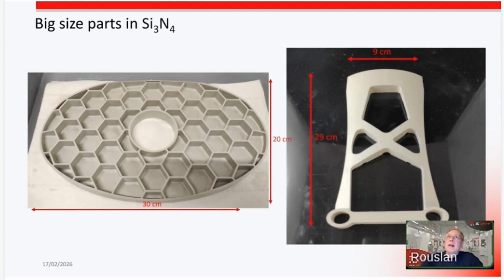So why am I saying this? It seems to be big, but when the shrinkage is repeatable and we really control it, we can apply the scaling factor. With some challenges, however. With machining, your part is fixed. You have a zero point to fix the part, so you can calculate, and using a more or less accurate tool, you can do your drilling, you can machine the part in a very accurate way. We don't have this in 3D printing. We have non-linear shrinkage. X, Y, and Z have slightly different shrinkage, but that's why we integrate all these software tools and AI to limit the impact of this on the final dimensional deviations.